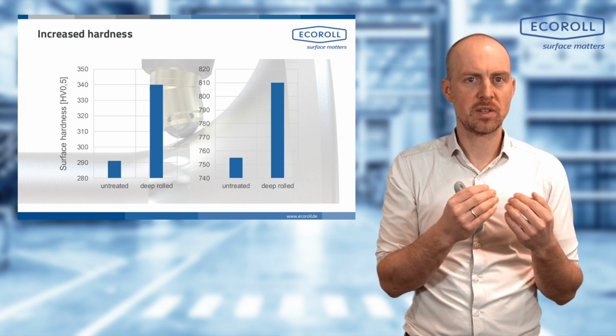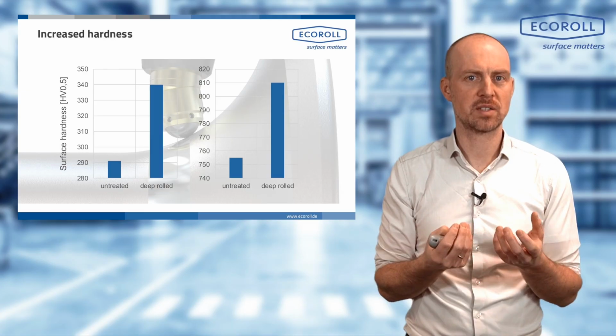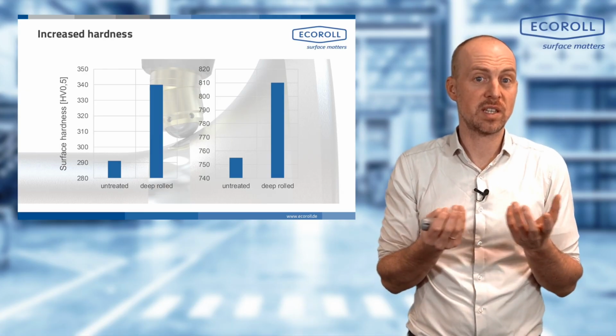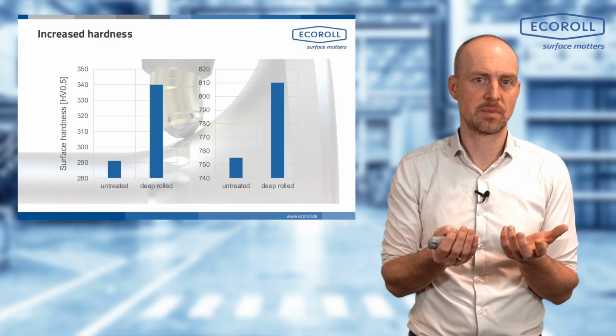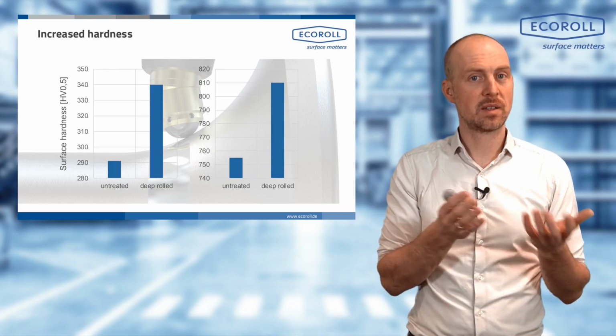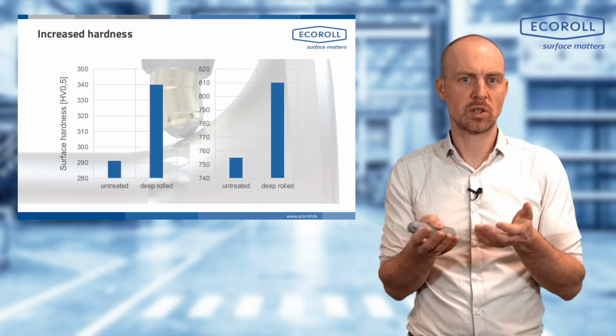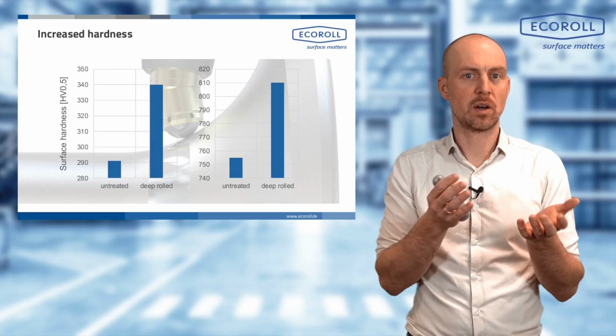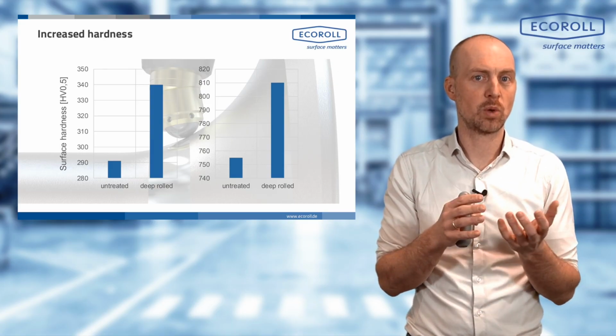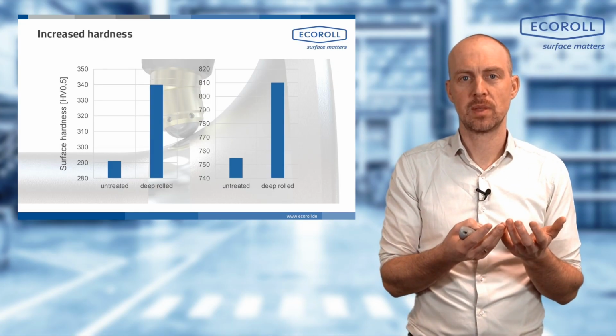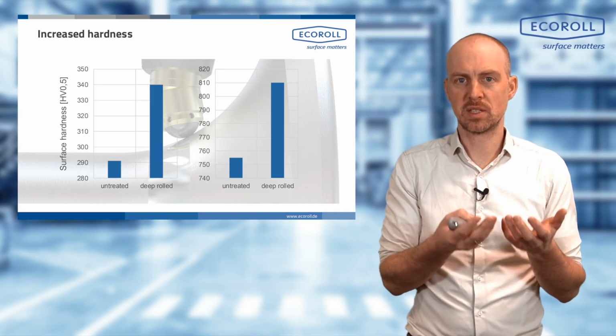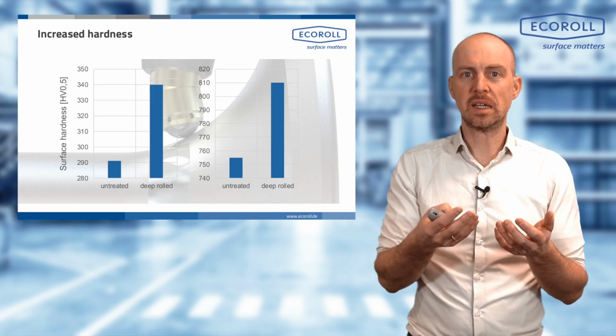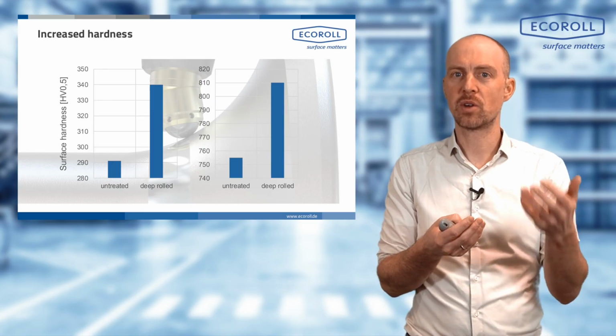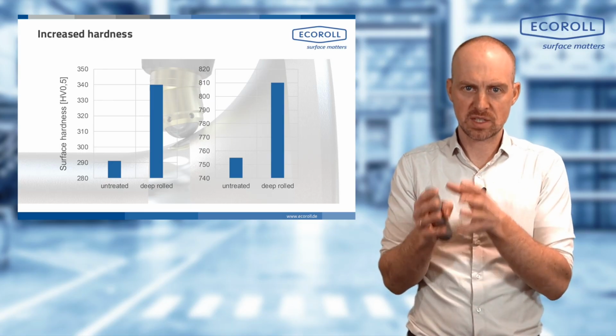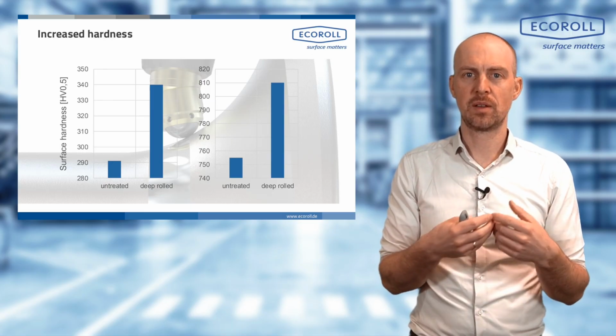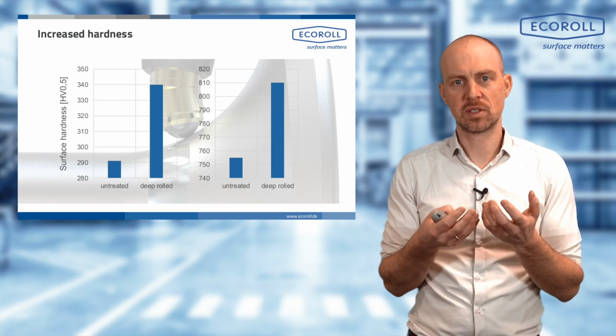There are also materials where this work hardening effect is so small that you can't really detect any increase in hardness. That also happens. There are other materials, so-called TRIP or TWIP steels, which transform martensitically through heat or mechanical stress. If I then deep roll these TRIP steels, which transform mechanically, I naturally get an enormous hardness increase effect. But that's because it's a special material. The penetration depth is also different, of course.